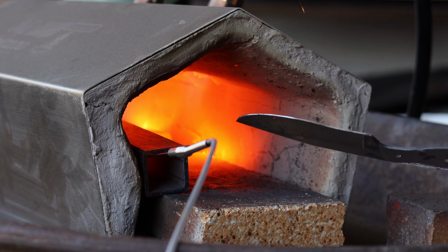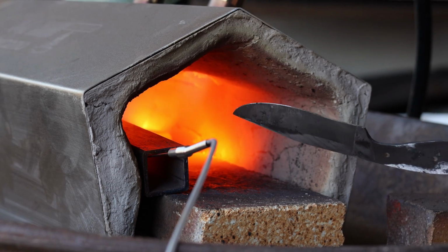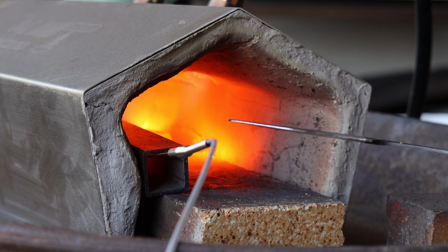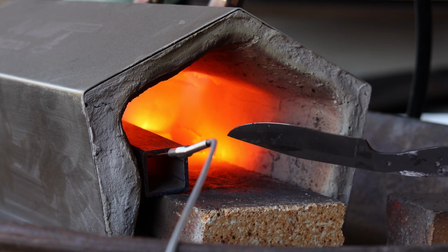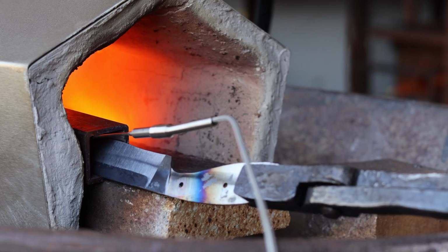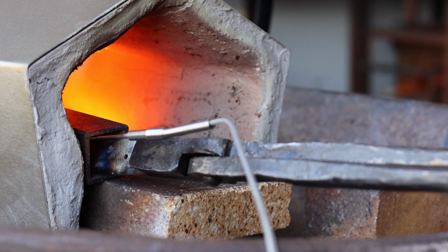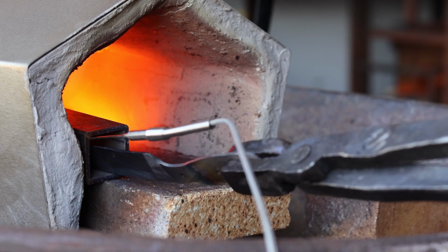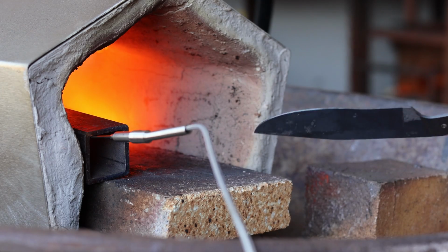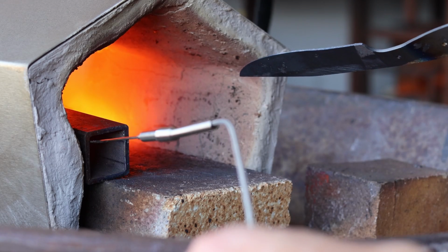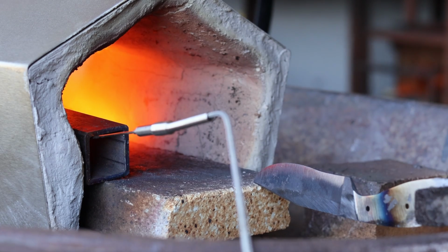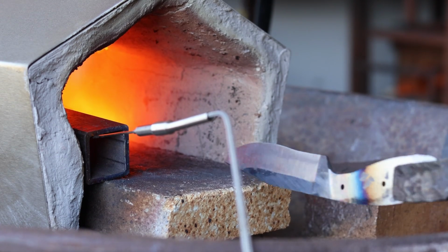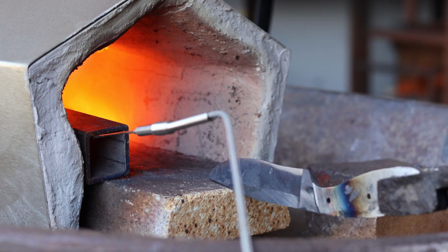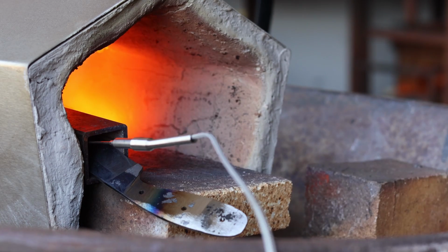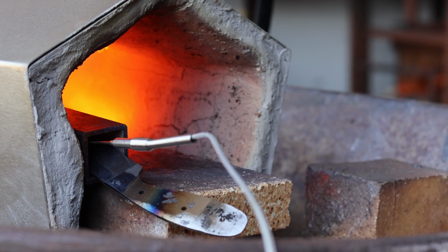normalizing cycle. I'm going to let this heat up real slow. I don't want to thermally shock the blade by heating it up too fast, because that could cause cracks. Now unfortunately, the point that I've got the thermocouple is one single point. So as I heat this blade up, in order to maintain it about 1650, I've got to kind of pass the length of the blade back and forth into and out of the hotter spots. I'm not going to make you stare at my forge for the next 45 minutes, so I'm going to do these normalizing cycles and I'm going to come back in a second.